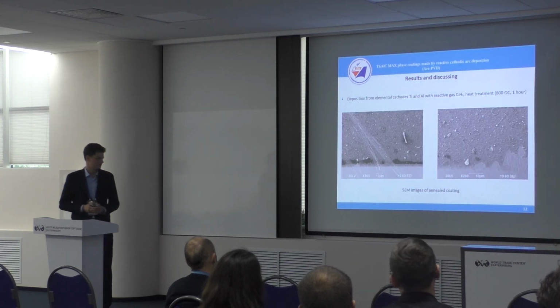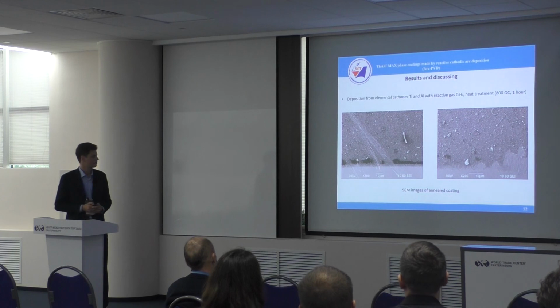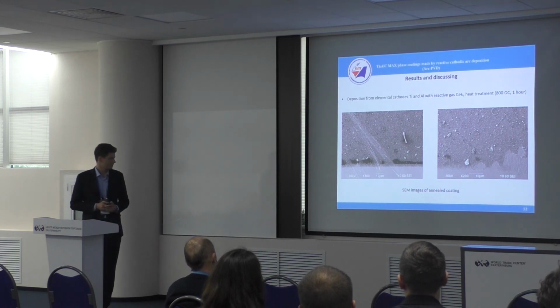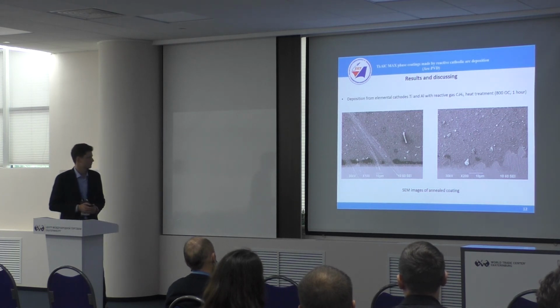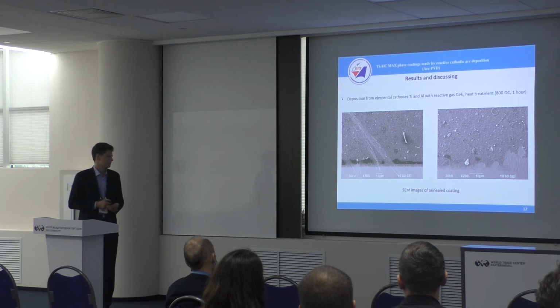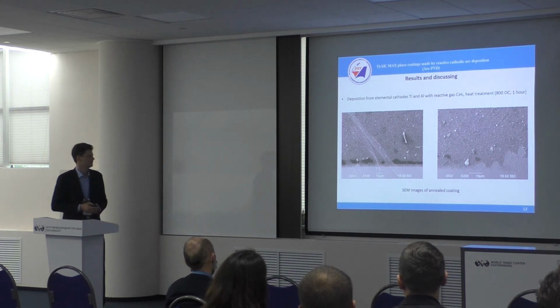This is scanning electron microscopy. As you can see, our thin films have a good microstructure with low porosity and some molten drops. This is a drawback of cathodic arc deposition.